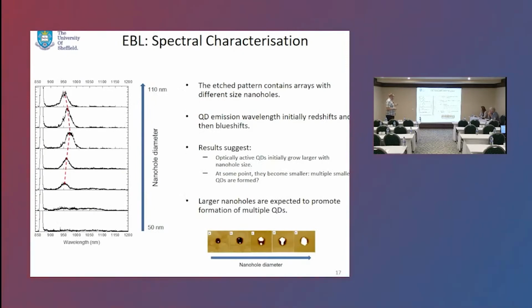If we look at the EBL now, we're taking one particular set of growth parameters and just looking at the effect of the nanohole diameter. So we start off with very small nanoholes and we don't really see much. And then once we get to a size where we're actually starting to nucleate dots in the pits, we get emission at around 960. The holes get a little bit bigger, the dots seem to get a little bit bigger and the wavelength goes up. And then it comes back again when we go to the largest sizes. Now remember that what we said might happen is when the holes get too large, we can end up with multiple dots in the pits and might be pulling the distribution back.